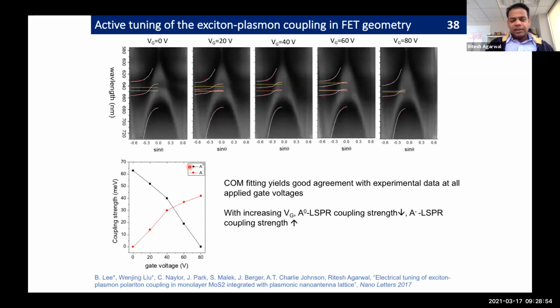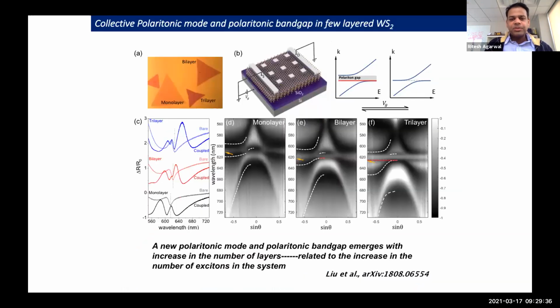We can extract coupling strengths by fitting this to a multi-exciton model as a function of gate voltage. At 0 gate voltage, 0 doesn't mean no extra charge, because these are generally intrinsically doped materials, but it means no external voltage applied. So we have a very strong coupling with the free excitons, and almost nothing with the trions. As we inject carriers, the coupling strength decreases for the free exciton, and for the trion it increases. So this basically gives us a handle to control light matter coupling strength in these systems.